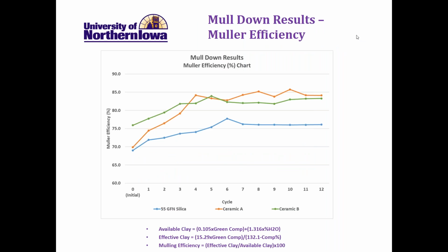If we take a look at what we call the muller efficiency, and that is how well we are developing those properties, you can see the calculations on the bottom of the screen. Once again, we see that the ceramic material had a higher mullering efficiency than the silica material did. This is an advantage. This means more consistent, higher properties with an engineered material.